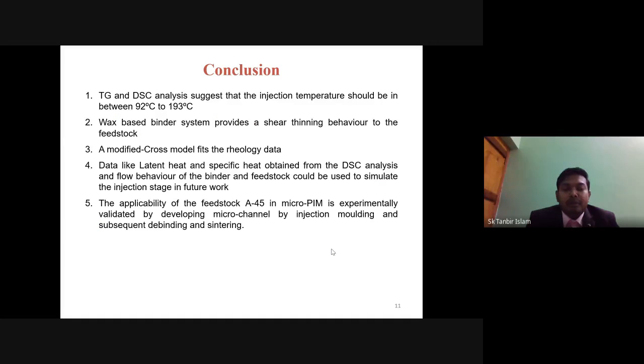The conclusion of our work is that TG and DSC analysis suggested the injection temperature should be between 92 degrees centigrade and 193 degrees centigrade, and the wax-based binder system provides a shear thinning behavior to the feedstock. A modified Cross model fits the rheology data. Data like latent heat and specific heat obtained from DSC analysis, and the flow behavior of the binder and feedstock, could be used to simulate the injection stage in future work. The applicability of the feedstock A-45 in micro powder injection molding is experimentally validated by developing microchannels by injection molding and subsequent debinding and sintering.